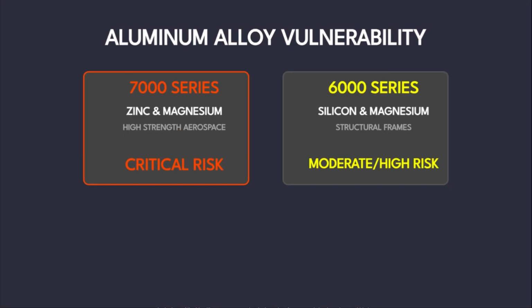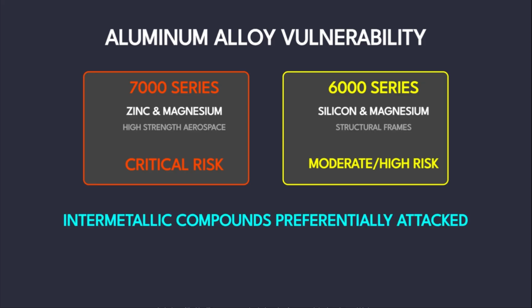Not all aluminum is created equal when it comes to gallium sensitivity. High-strength aerospace alloys, such as those in the 7000 series containing zinc and magnesium, are particularly vulnerable. These alloys often have complex grain boundary chemistries designed to inhibit dislocation movement, which provides their strength. Gallium exploits these specific microstructures more aggressively than it does with pure aluminum. In contrast, the 6000 series alloys, commonly used in structural frames and containing silicon and magnesium, show slightly different rates of penetration, but are still ultimately susceptible to failure.